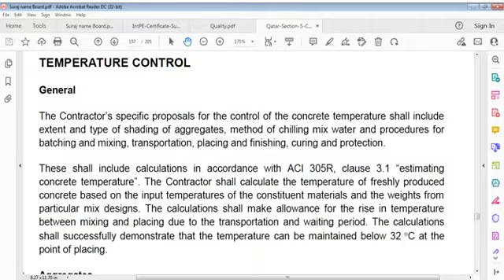It says, contractor shall calculate temperature of freshly produced concrete based on input temperature of constituent materials and weights from particular mix designs. Calculation shall make allowance for rise in temperature between mixing and placing due to transportation and waiting period. Calculation shall successfully demonstrate that temperature can be maintained below 32 degrees Celsius at point of placing.